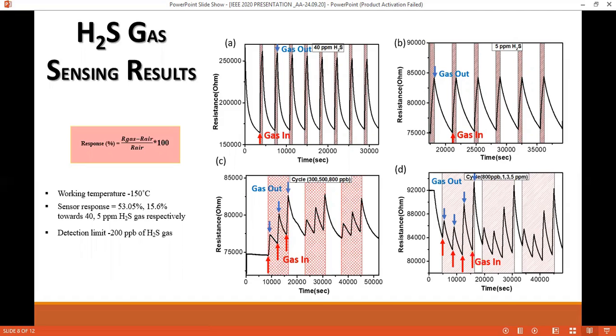The gas response is calculated using the equation given here, where R gas corresponds to the resistance of the sensor in presence of H2S gas and R air corresponds to the resistance of the sensor in presence of synthetic air. The sensor response was calculated to be 53.05 towards 40 ppm of H2S gas and decreases down to 15.6% when the concentration is reduced to 5 ppm.